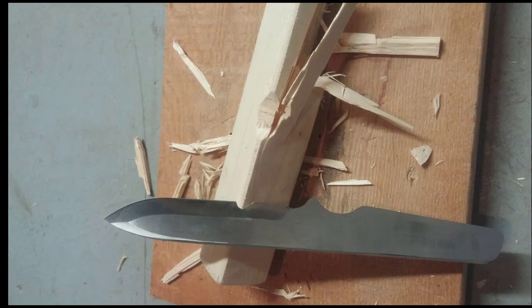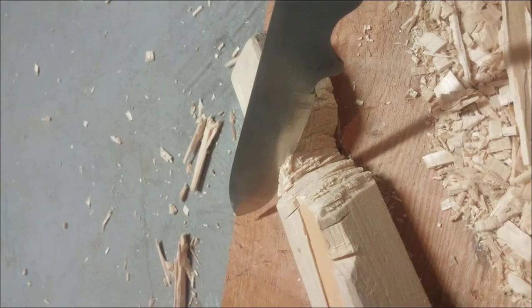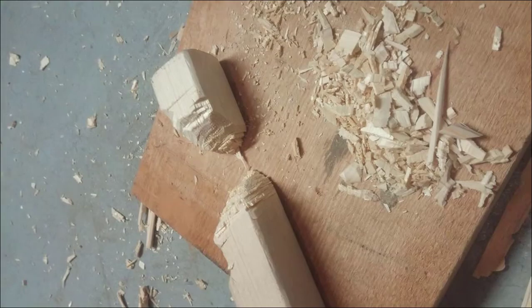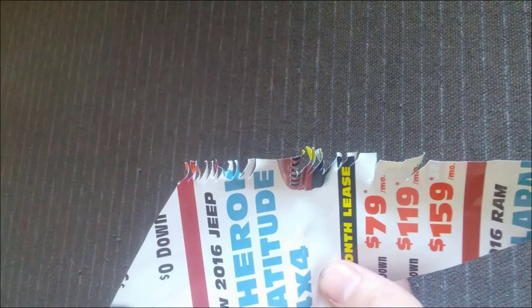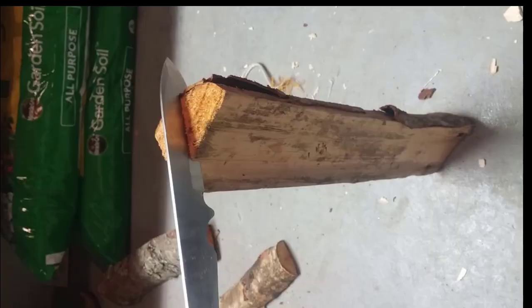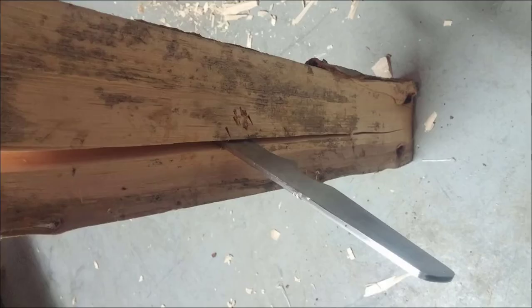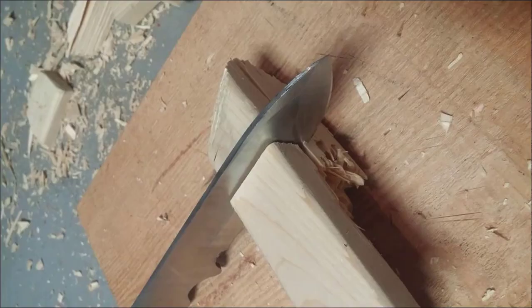Tests. Hardness, I got around 59-60 HRC for the blade. Due to this being my first heat treat, the tip didn't get as hard as it should have. Tip retention, I had a 2x2 that I jammed the tip into and then continually pried it out. The tip was not damaged. Chop test, I chopped my way through an entire 2x2. Cutting paper showed it was close to, if not just as sharp as before testing.